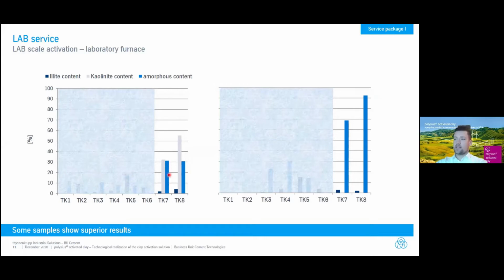So the target of activation in this case for this customer was to fully activate the kaolinite content. And this is what I would like to show you now on the right-hand side. So here you can see the illite is nearly the same as before. So we did not activate the illite because this was not the target. We can do it, then we have to go to higher temperatures, but we did not because it was not the target in this case.